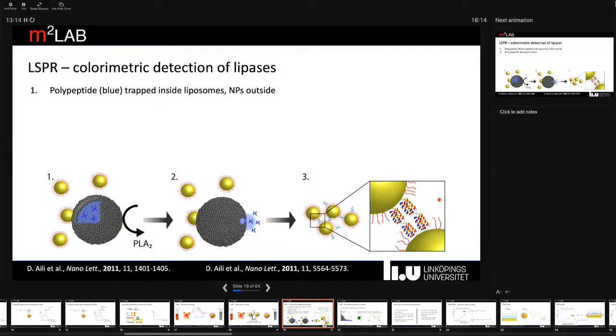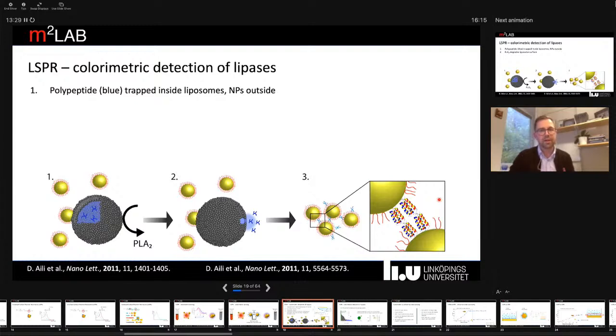This is one example from our work, where we have been developing sensors for lipases, which are a large group of enzymes that hydrolyze lipids, and also highly interesting and relevant biomarkers for a range of diseases and drug targets. Lipases hydrolyze lipids, so the substrate is, of course, a lipid bilayer. So, to go about this, we encapsulated a designed peptide inside liposomes, and this peptide is designed in such a way that it can trigger aggregation of gold nanoparticles that are functionalized with a complementary peptide, and these particles are kept outside the liposomes.